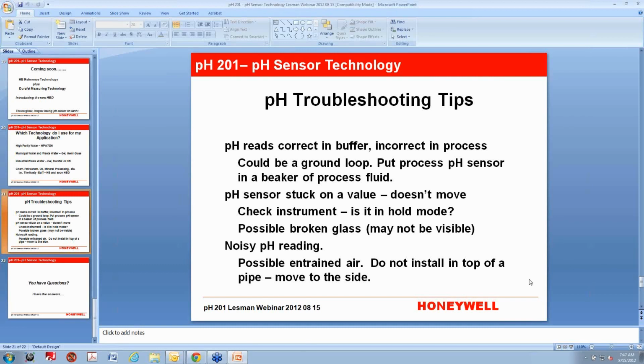And you would see that with any pH sensor. A DuraFET would be a little less susceptible to it, but only a little, because we're still talking about a pretty small signal. But the test is to put it in this beaker of process fluid. If it reads correctly, the odds are really, really good that you have a ground loop.